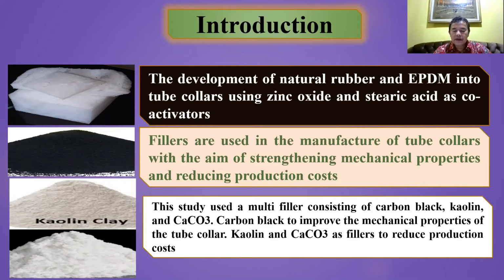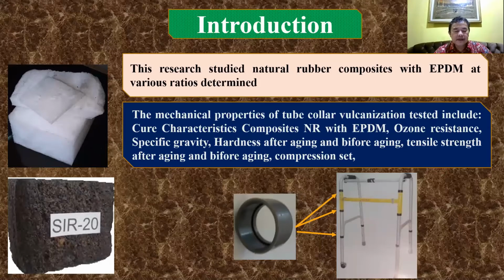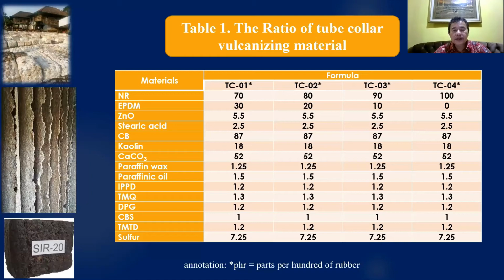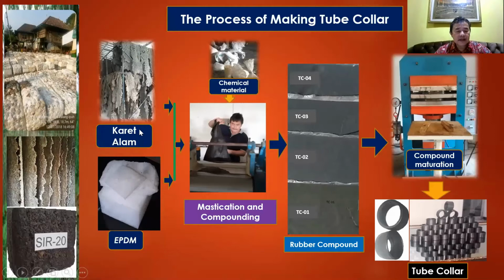This research studied natural rubber composite with EPDM at various ratios, and determined the mechanical properties of tube collar. Parameters tested include cure characteristics of the composite of natural rubber with EPDM, ozone resistance, specific gravity, hardness before and after aging, tensile strength before and after aging, and compression set. This Table 1 shows the ratio of tube collar vulcanizing material, with formulas TC01, TC02, TC03, and TC04. The process of making tube collar involves natural rubber, EPDM, chemicals, mastication, rubber compound, and compound maturation and tube collar.